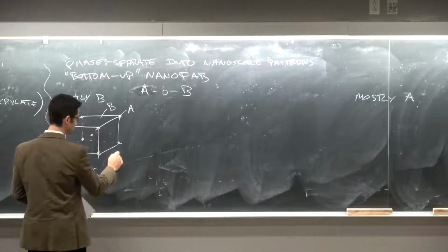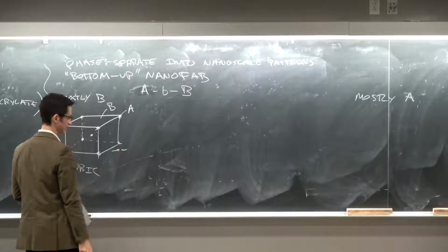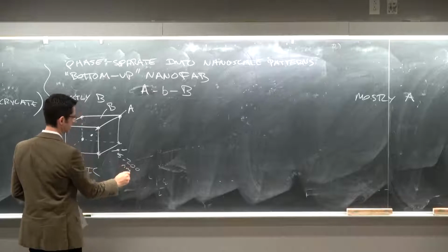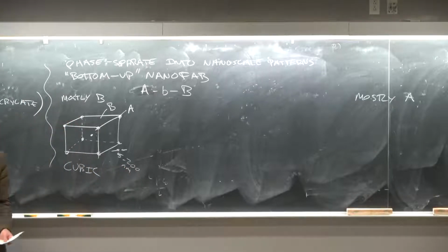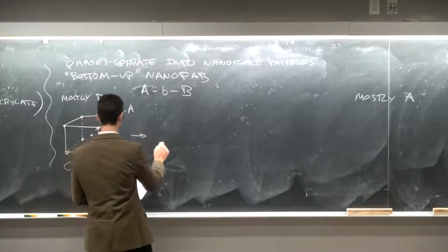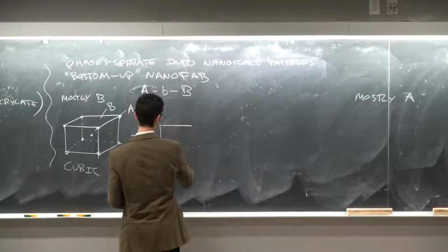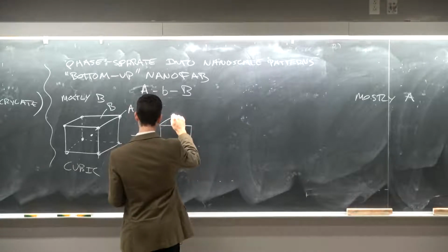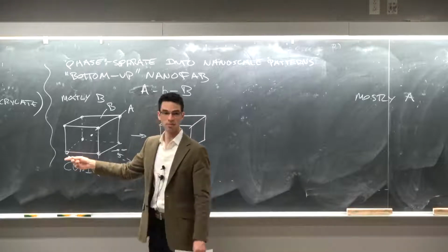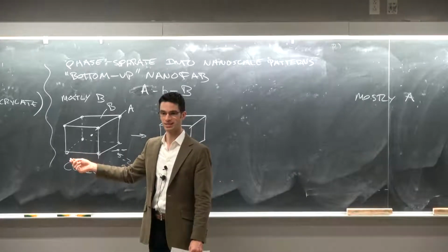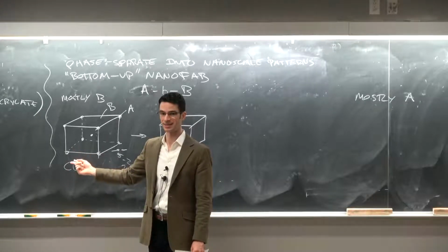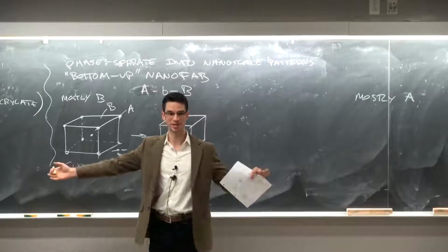And these domains could be somewhere on the order of, let's say, 5 to 200 nanometers. Those are characteristic sizes of all the structures that you'll find in block copolymers. As you increase the amount of A, these blobs become bigger and bigger until there's a thermodynamically more favorable state for these to be in, where they stretch out and become cylinders.